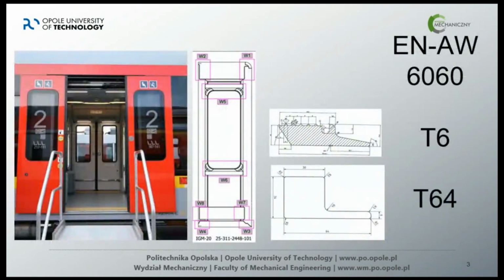This is the door system, and we look at some parts of it. We see the doors in the middle, and we take specimens directly from the profiles used in these doors. On the right you see the T6 aluminium profile and the T64 profile. Every specimen is taken directly from these parts, not from the factory. It is very important for use in factories.